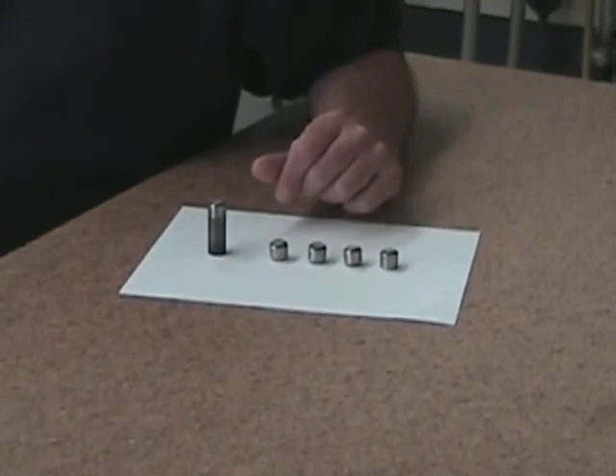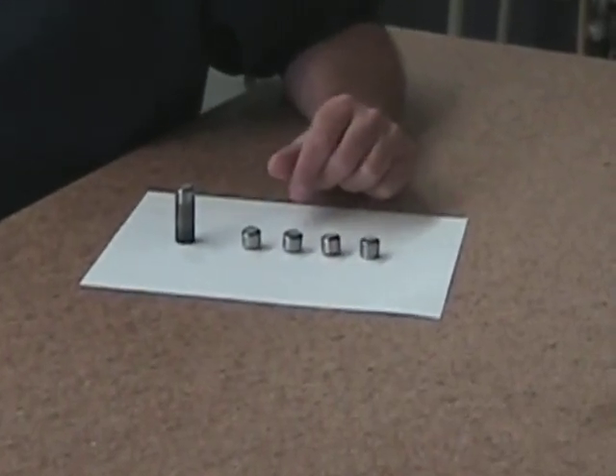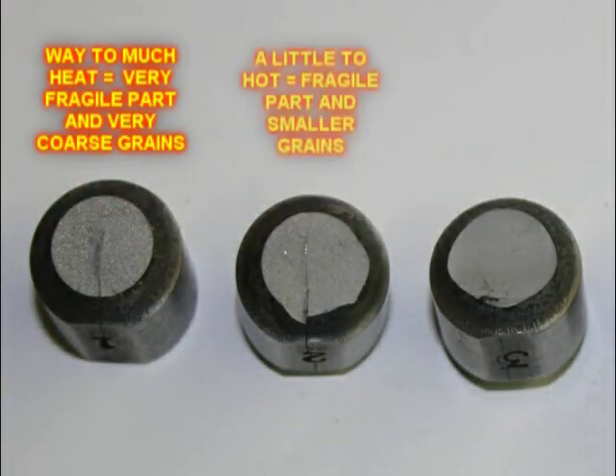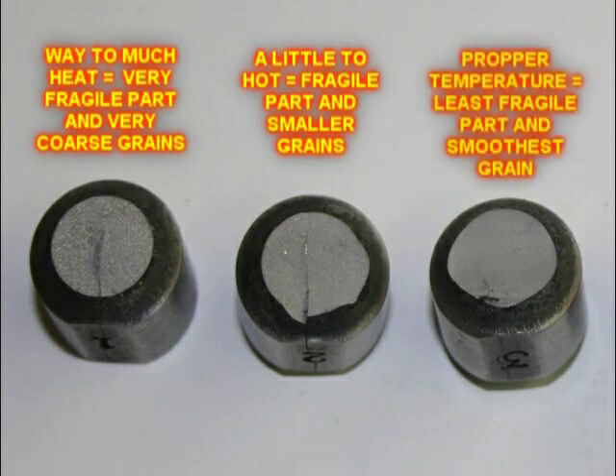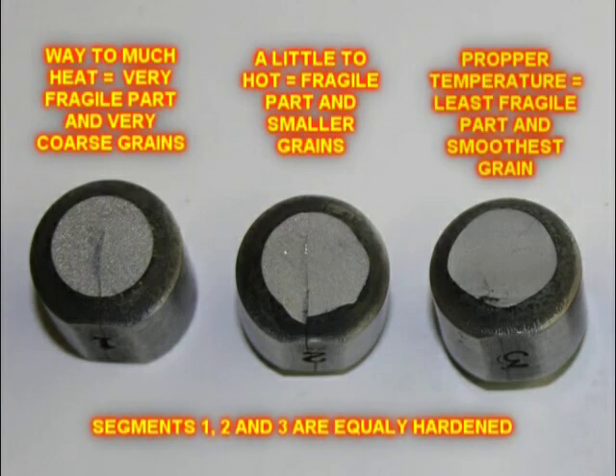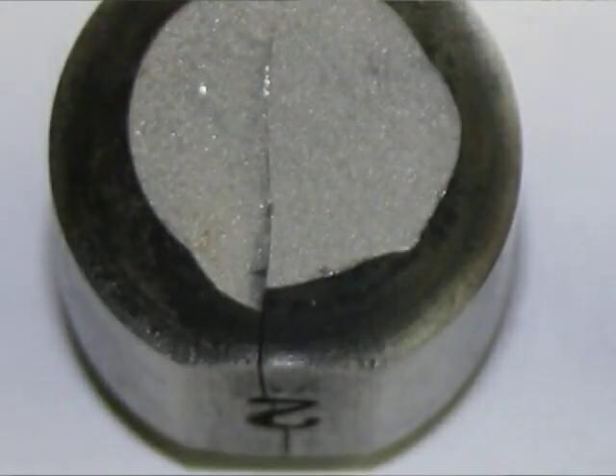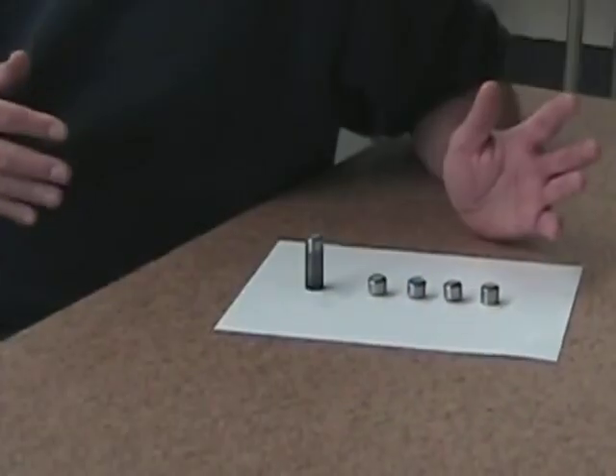What does that tell us? Knowing that section 1, 2, and 3 are the same hardness, but that the steel is not as tough or difficult to break the higher you go. Remember, section 1 was very hot. Section 2 was too hot. Section 3 was about at the right area. So this tells us that even though they're the same hardness, the temperature that you quench steel at has an effect on how tough it is. Actually, the hotter a steel is in its critical temperature range, the larger the grains of the steel get and the easier it is to fracture that steel.